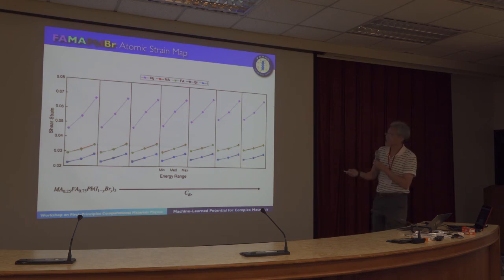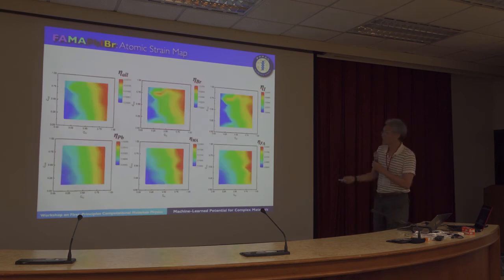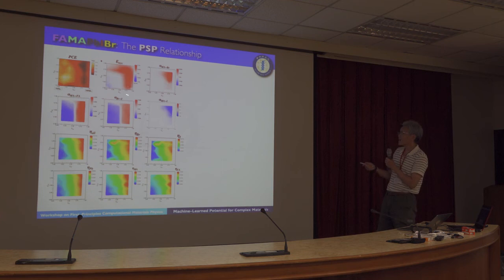Okay, so the next thing is the map of the atomic strain. So here you can see that when energy drops, the atomic strain also drops. These are for all the different elements. So no matter the concentration, when the system energy drops, the atomic strain also drops. And this is the map of all the atomic shear strength. So this is the average, and this is the bromine, iodine, lead, methylammonium, and the bromine. And then finally, we have done this many methods, and this one is from experiments.